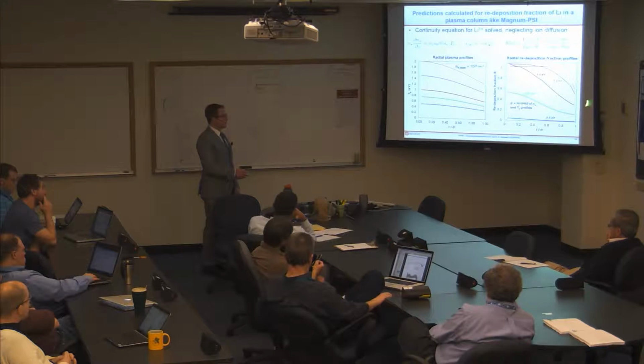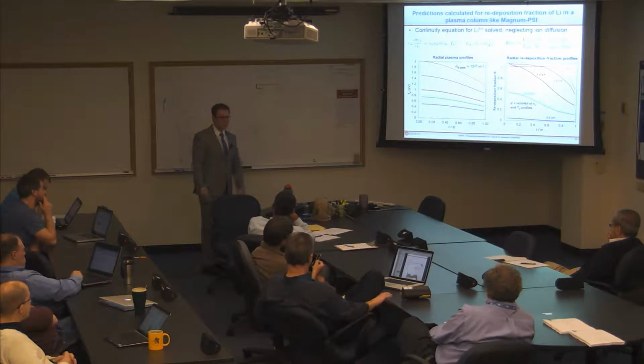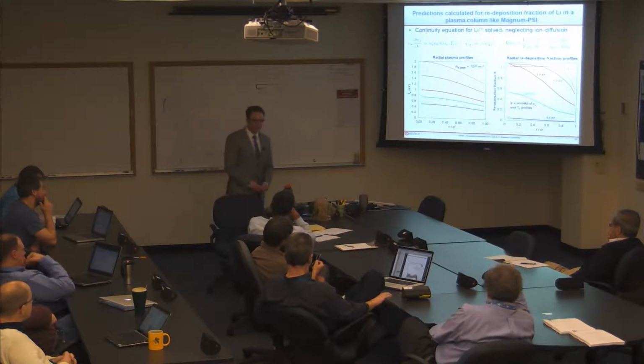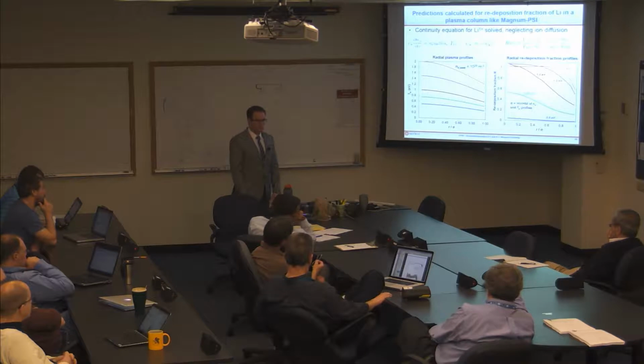And then near the edge, you get this decrease because some lithium atoms are still eroding off the edge of the target, and those are just assumed lost from the plasma. So this diagram on the right includes ion diffusion. This does not include ion diffusion. Then how do we get bigger than 1?